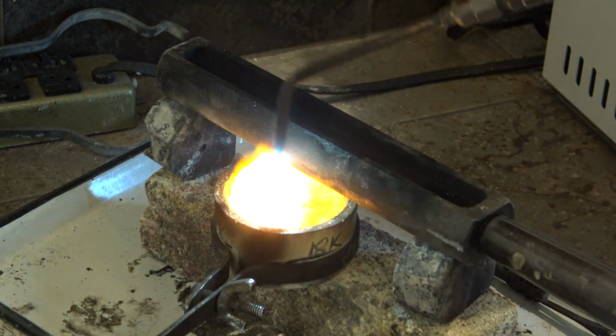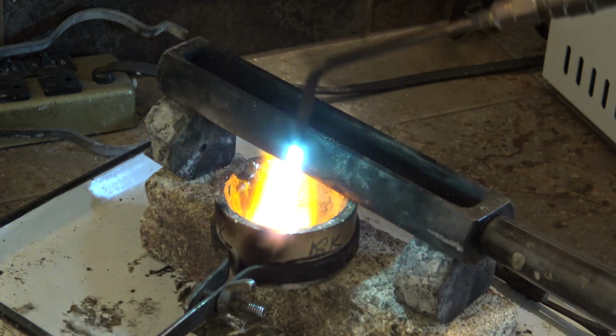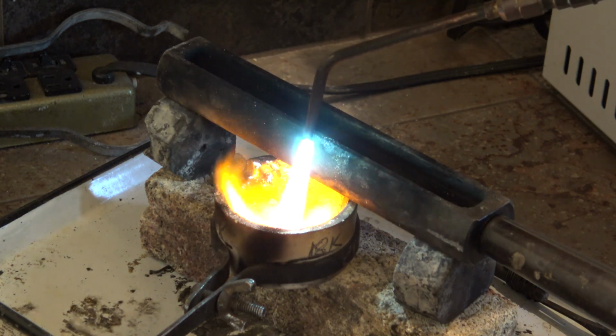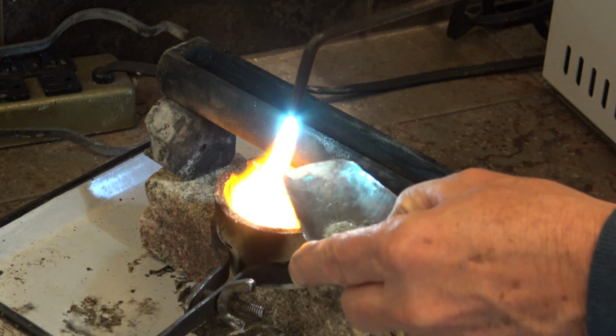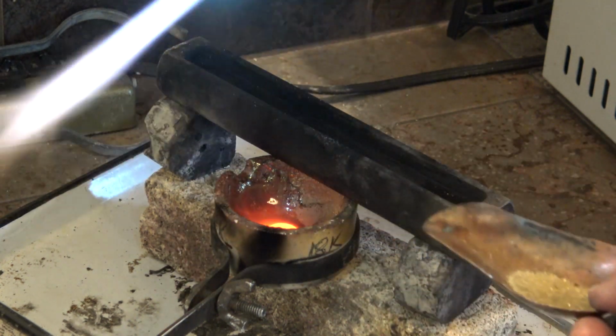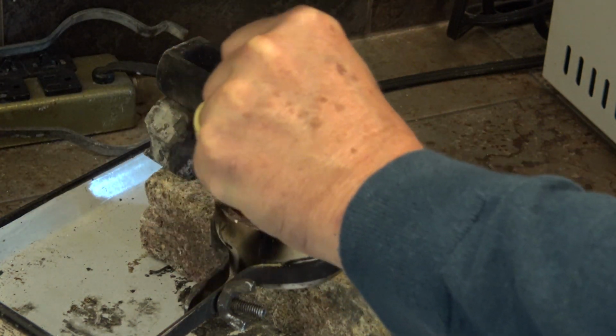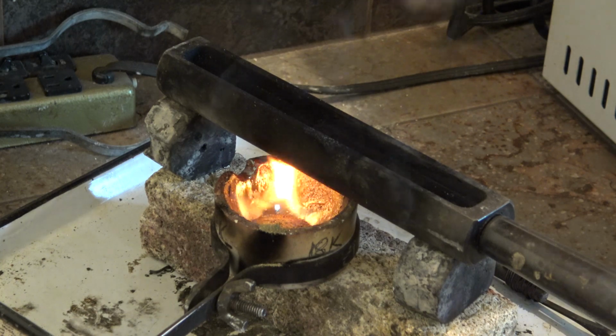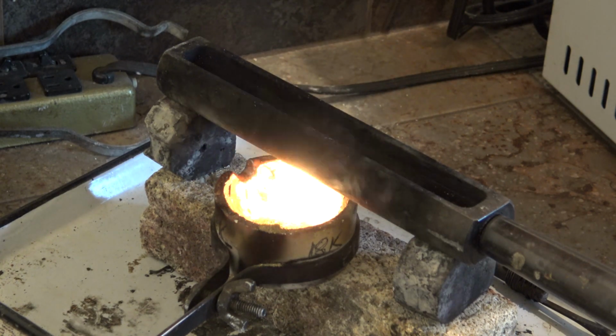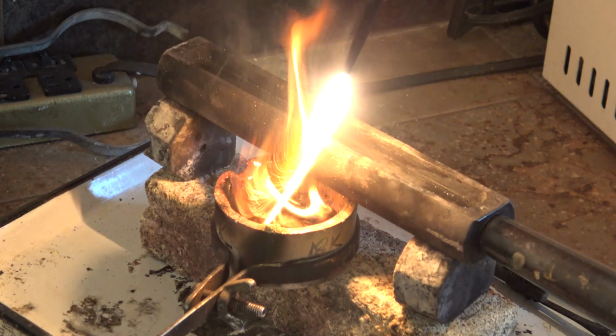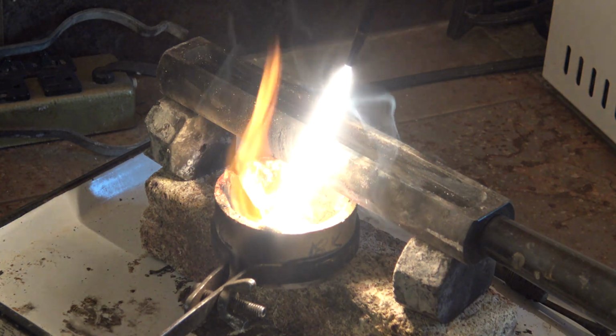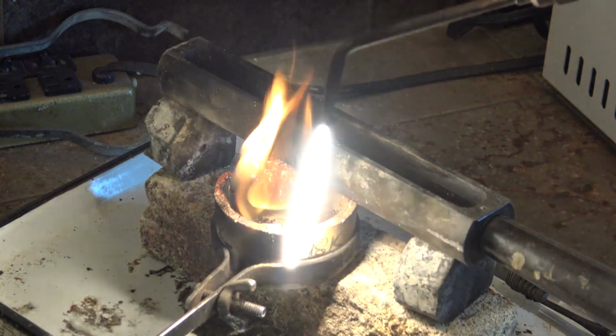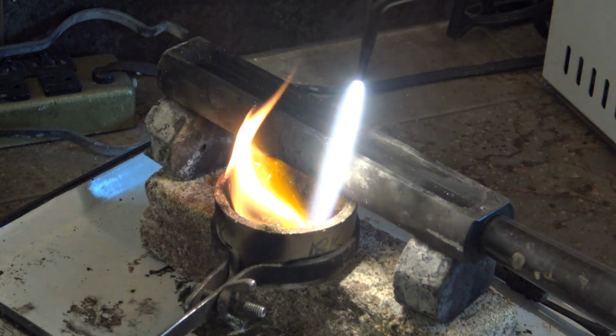You'll see there's a little bit of borax on the end of the rod. It picks up the molten excess flux as you're working. So I remove my flame and dump the filings down right on top of the puddle. And then I immediately reduce the flame to a very reducing soft flame that doesn't blow very hard. So it's a soft flame.